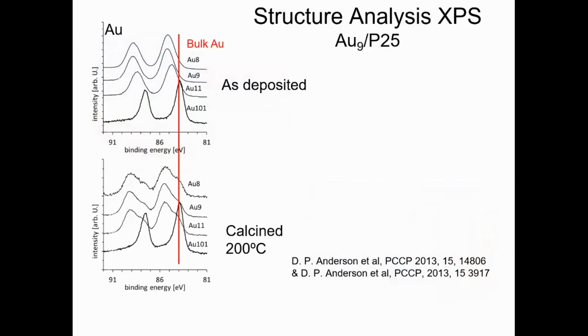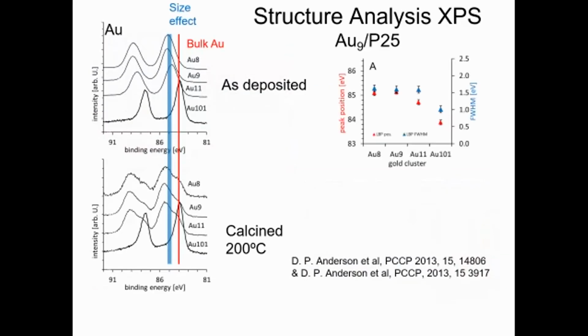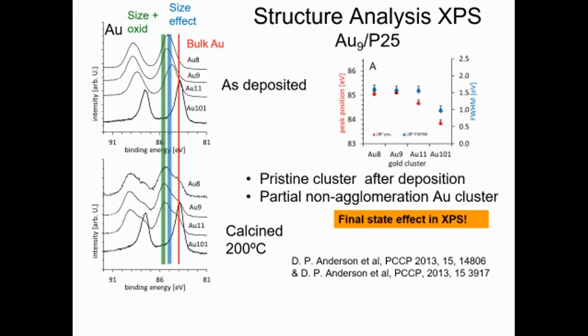We did a study at the synchrotron, and we show there is a huge difference between gold 8, 9, and even 11, and gold 101 atoms, depending on the peak. This is what's called the size effect of XPS, and it is related to the final state effect. What is the final state effect? It means that the cluster itself gets a charge state when the photon hits, and it takes a period of time to relax, and this relaxation is a fingerprint of these different clusters.